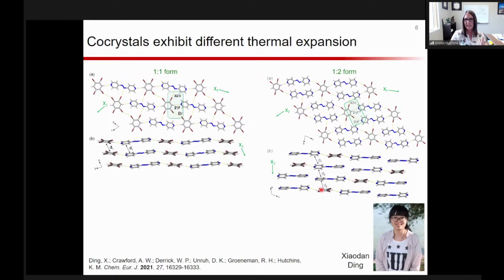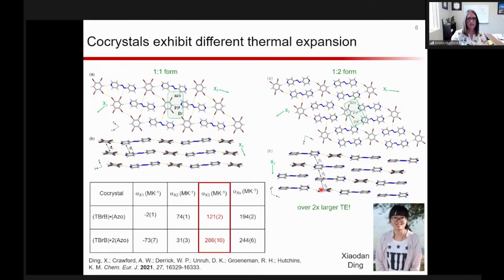And so I won't go into the details of the thermal expansion analysis, but one of the key take homes was that because of that difference in pi stacking arrangements, we actually got 2 times larger thermal expansion values in the 1-to-2 form when compared to the 1-to-1. So a coefficient of 121 versus 286. So even though you have the same molecular components in the co-crystal, because they are arranged differently, you can get differences in properties.